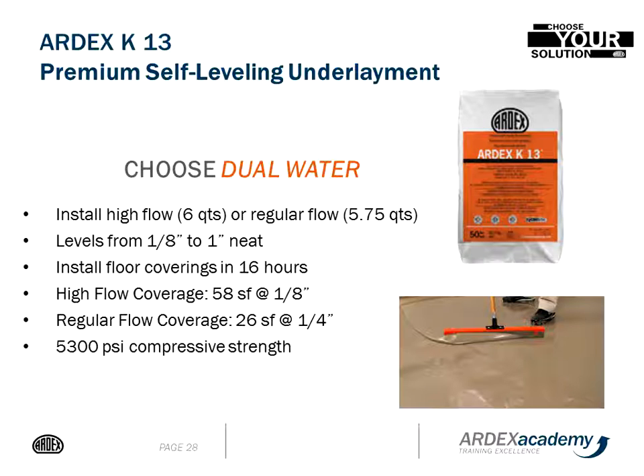So with a high flow material, it's a lot more liquid than a regular flow. You're able to pour thinner, and if your floor is flat already and it just has an epoxy mitigation system on, or maybe you have epoxy terrazzo and we just need a cementitious blotter layer, using K13 at the high water ratio, 6 quarts of water, allows for an 1/8 inch application over something like terrazzo or a mitigation system. Using the spike roller, you get an extremely flat surface, smooth enough for flooring, but yet you're only installing it at 1/8 inch.